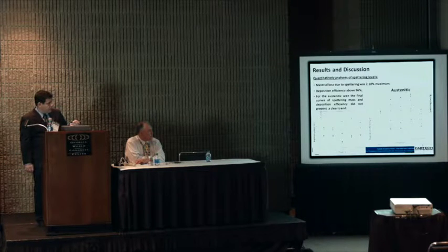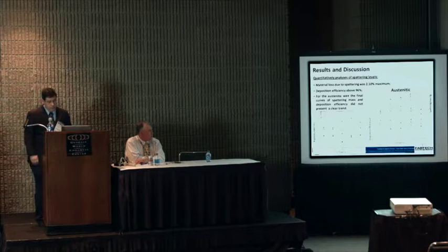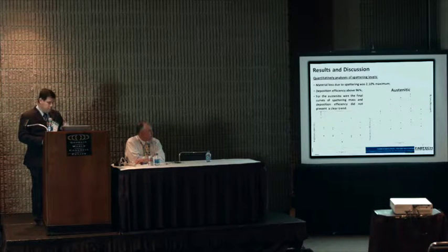Spattering in our case was really low, 2.10% maximum, so you have an efficiency of, let's say, 97.9%, which is pretty good. So just 2% of material flying away from the weld pool. So the deposition efficiency is above 96%. The difference here could be fumes, small silicates that stay aside of the weld bead, things like that.